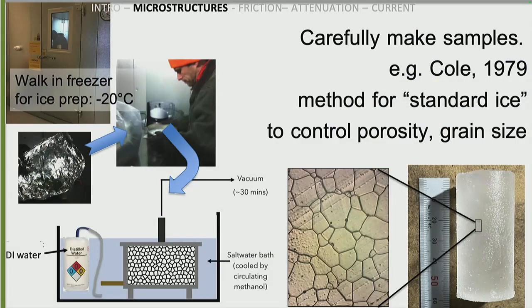How do we make it? Well, we get all bundled up, a little bit like you all are today in this room. We get in our walk-in freezer, and we make a multi-step process of coming up with these controlled samples. We're following in the footsteps of David Cole from CRREL, who developed this practice so that lab to lab, we can all follow this method and compare our results. So we make some seed ice in a bucket. We then grind it up with a food processor, sieve it, pack it into a die, pull a vacuum on that die, and then introduce, in the case of these pure ice samples, distilled water. We then freeze it on a cold plate. And so what we get is really uniform, foam texture ice, very low porosity, uniform grain size top to bottom, sample 1 through sample 100. We're pretty confident with this.